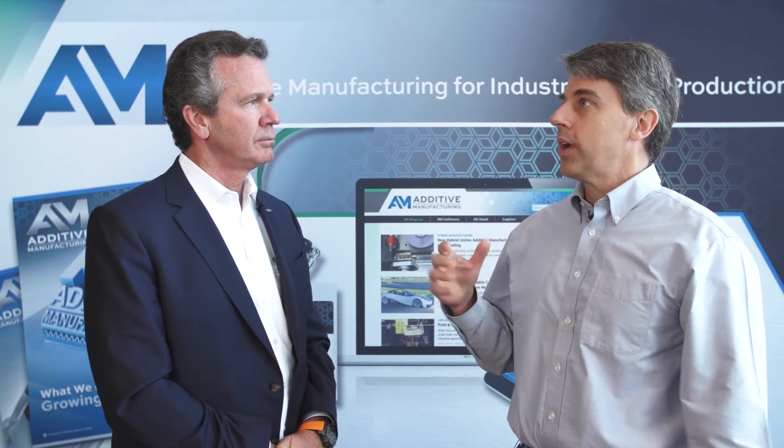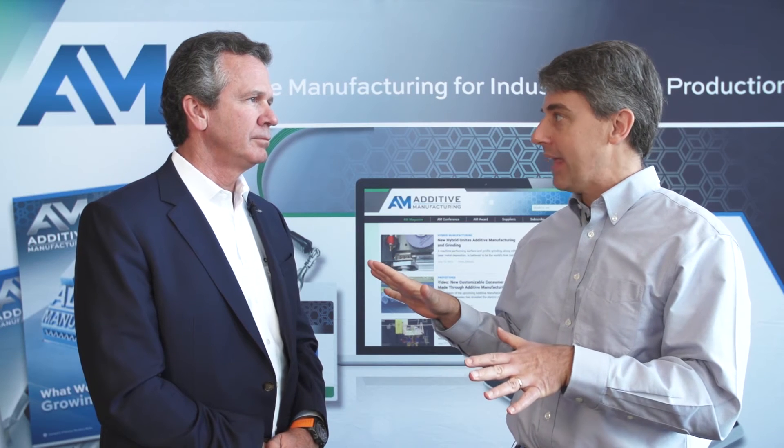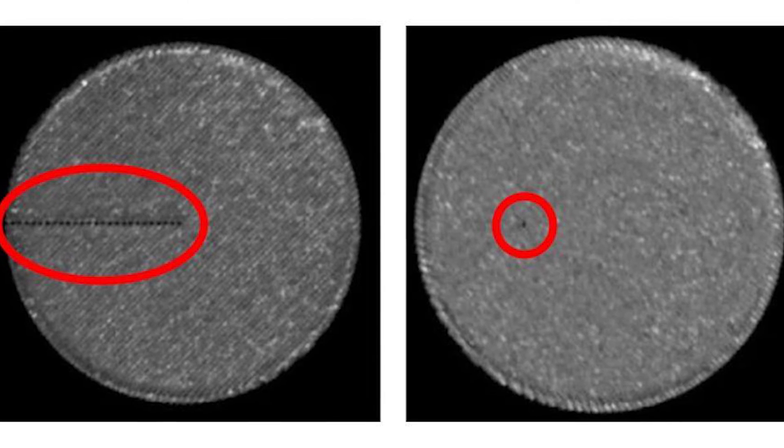What kinds of data can an additive metal process provide related to quality control, and how is your technology advancing in that area? Almost a decade ago, Frank saw the need to monitor and document the process — otherwise you're just making widgets. He started with a product called QM Melt Pool, and we've just released the QM Melt Pool 3D. We're looking directly through the laser into the powder bed and into the melt pool, measuring the intensity as well as the shape and area of the melt pool. We compress that data and produce a three-dimensional model of the entire build that will show any porosity or if the laser went to sleep for two nanoseconds. We're hoping that will help companies certify their parts, whether for the FAA, the FDA, or any internal certification processes, giving people confidence they're building quality, flaw-free parts.